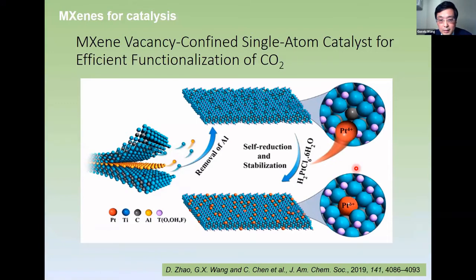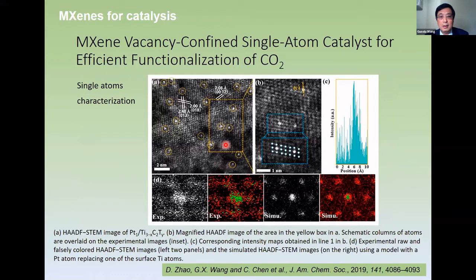And then my friend in Tsinghua University, Professor Chen Chen, they did a similar work. In this case, we use a chemical method to deposit Pt single atoms on the surface of MXene nanosheets. We use this catalyst for functionalization of carbon dioxide. So this is the HRTEM and HAADF-STEM analysis. You can see using chemical method, you can also obtain platinum single atoms deposited on the surface of the MXene nanosheets.